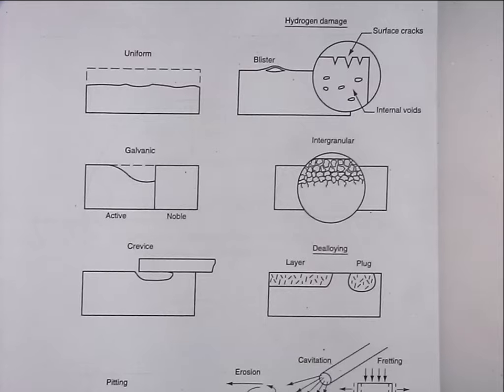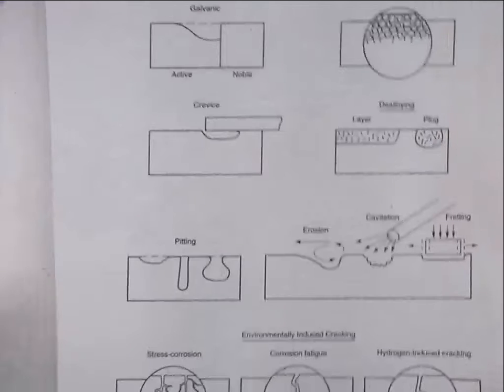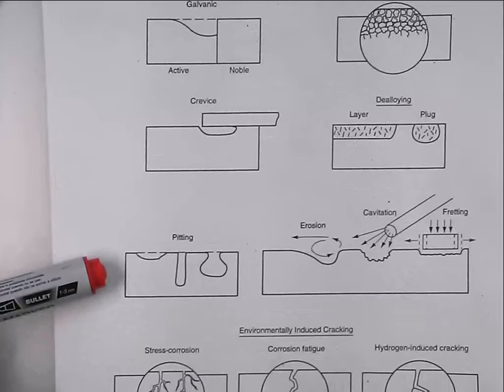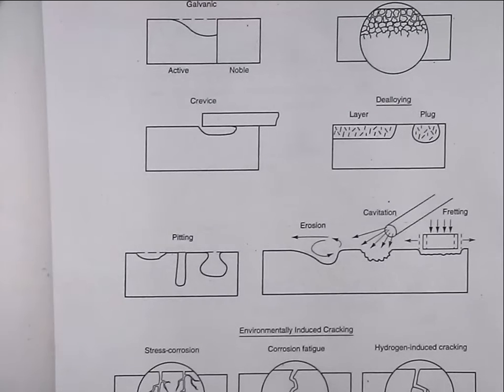If you remember, we were talking about modes of corrosion, and we'd started looking at localized corrosion because that's a very significant proportion of the failures that occur, and we'd looked at pitting corrosion with the water droplet as an example on a surface, but also where you get a protective coating that is damaged, and then all the anodic current is concentrated in one location. And I showed you some samples of materials that had pitted, both pitting from the outside of the pipe in over and from the inside of the pipe out over.